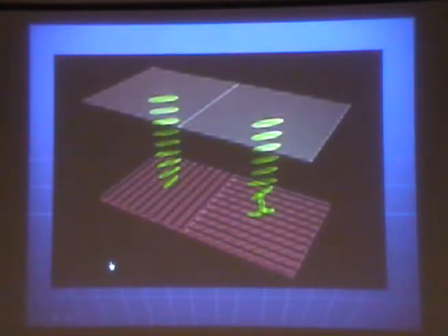So the essential part of this transition is that because we have two domains that have different topological connection, we can induce a higher twist angle that is larger than 90 degrees, and that can allow us to induce the electric field induced buckling transition.